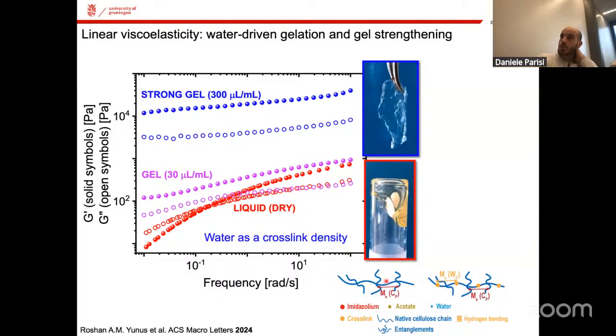Therefore, the plateau modulus or the elasticity is dictated by how tight this network is, or the molecular weight between two consecutive entanglements. On the other hand, this low frequency elastic modulus is dictated by the crosslinks that we are forming because of the water addition. So we are going to have effective double networks. The first network is exerted by the entanglements, and the second network is dictated by the crosslinks. If you prefer to see it this way, water acts as a crosslink density. The more water you add, the more crosslinks you form, and the tighter the network becomes.